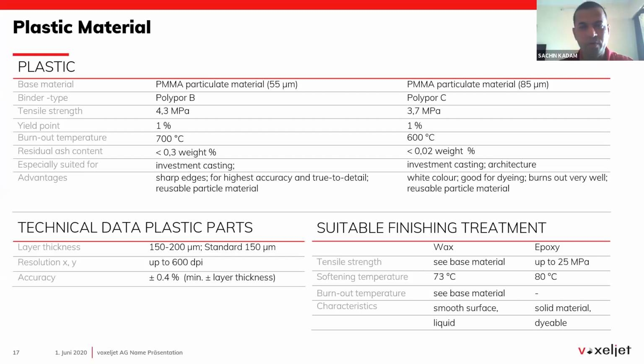Okay, so the video explains a lot of things. Normally after the printed parts, we do wax coating, because we need to get a good surface finish, and also it avoids the shrinkage of the parts. For the plastic or PMMA process, we use different types of material, the powders PolyPor B and PolyPor C, for different applications. They have different surface finishes and different strengths, and these can be easily burned out at 700 degrees Celsius for the investment casting. Normally the layer thickness for the printing is 150 micron, and the resolution is very high, up to 600 dpi.